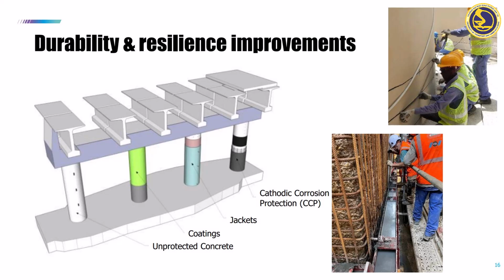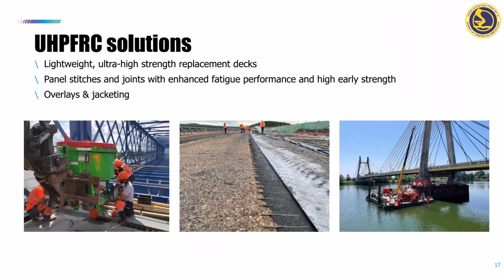and it was decided to install a durability jacket using such a UHP-FRC solution. You see in the picture in the middle what it looks like. On the left, you see a surface of a bridge deck prepared by hydrodemolition or high-pressure water jetting. And on the right, you see the applied UHP-FRC material. In the dark zone, you see a bit the steel fibers. So a thin overlay as a waterproof durability layer.